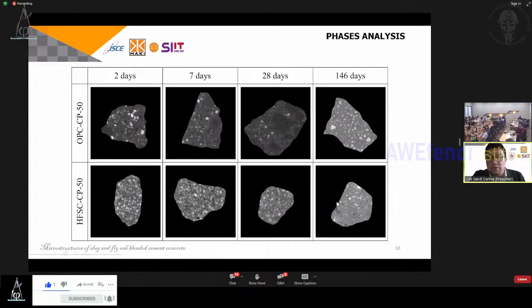And here I show you the image, one slide from the X-ray CT. We have a bunch of slides. If I'm not mistaken, it's around 2,000 slides, similar to bread. If you cut the bread, you will have slices, and then if you merge the slices, you have a 3D, similar to this one. This is at 2 days, and then 7 days, 28 days, and 146 days. This is from a similar specimen, but a different sample.